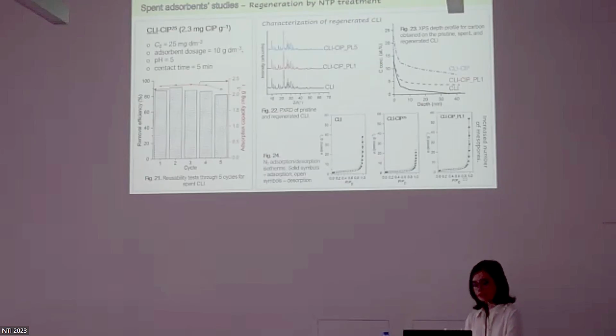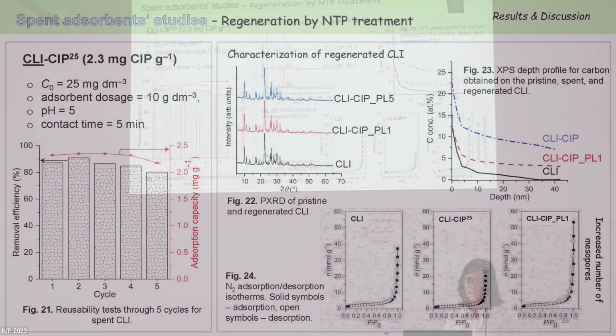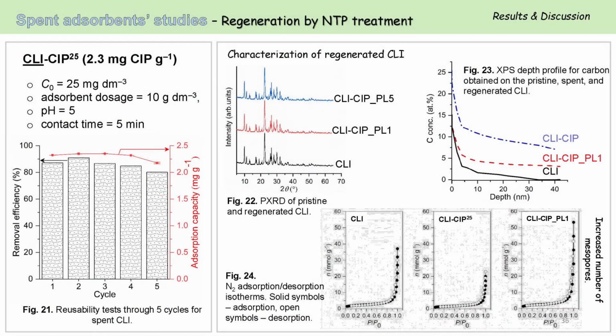Then we reduced the concentration and the results were much better. The removal efficiency for the spent clinoptilolite with lower ciprofloxacin concentration shows a practically stable trend of constant removal efficiency. It degraded by maybe 10% in the 5th adsorption cycle, which indicates a good result.